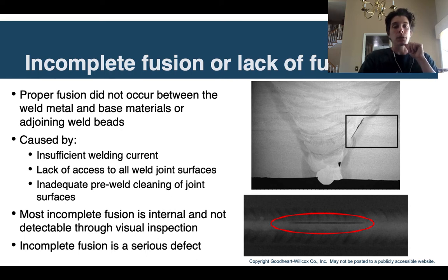Another problem, incomplete fusion or lack of fusion. Another thing I'm sure you've encountered before. This means that proper fusion did not occur between the weld metal and base materials, or between adjoining weld beads if you're doing a multi-pass weld. So this is between the base material and the weld bead itself. There's a lack of fusion there. This is some lack of fusion, it looks like, in between the weld. Maybe that is between weld beads.